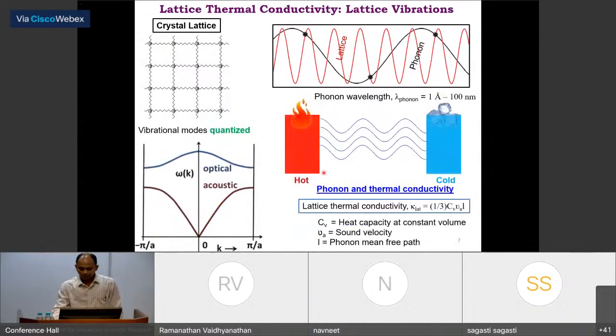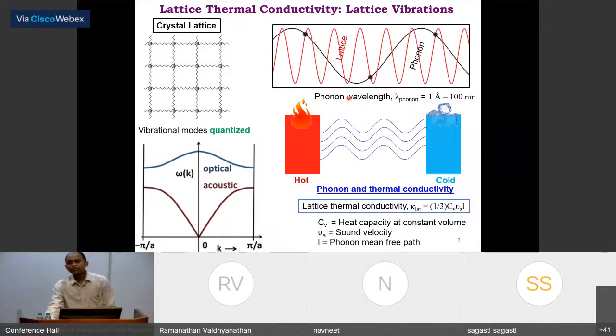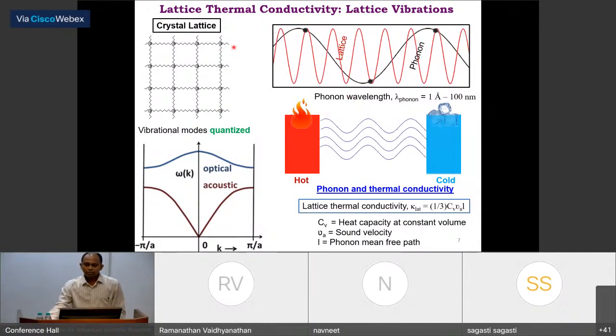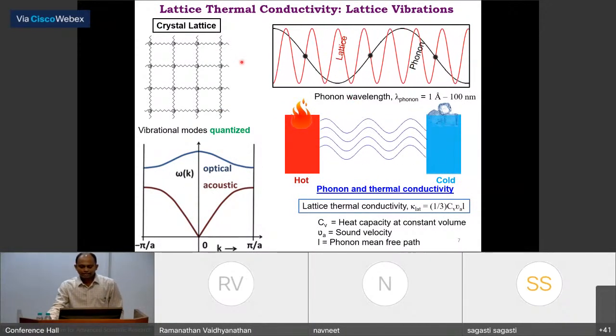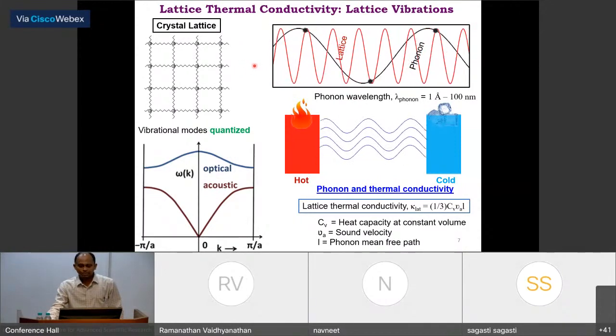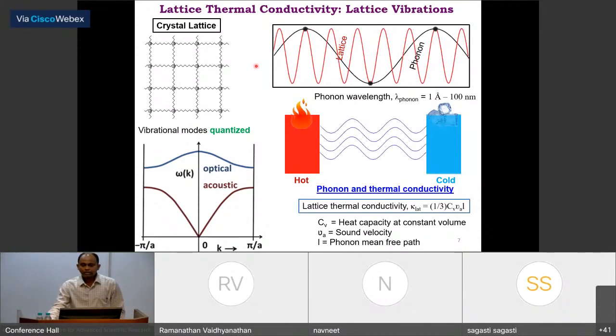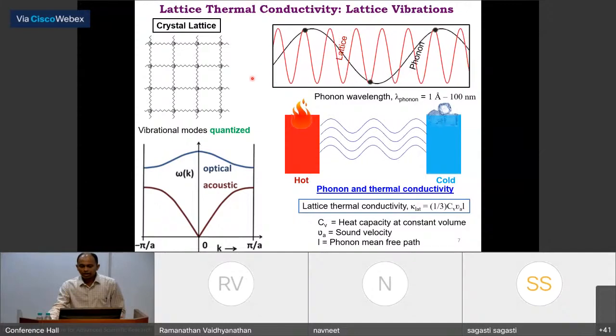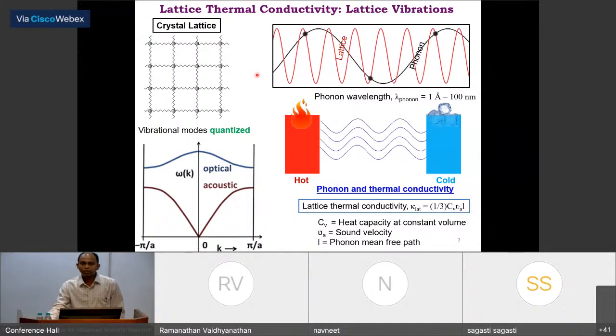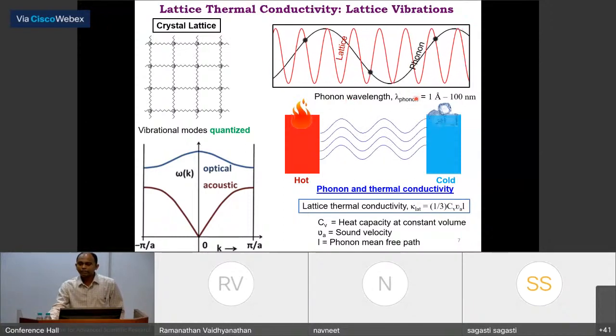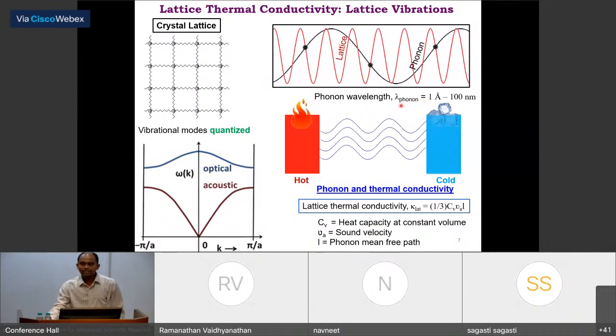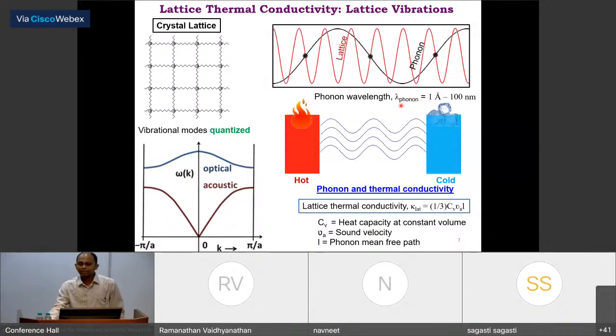So now I come back to this lattice thermal conductivity, which basically carries most of the heat in a solid material. So lattice thermal conductivity is nothing but how phonons carry the heat, and phonon is basically quantized lattice vibration, and the phonons which carry the heat in solid tellurides and selenides have a mean free path or wavelength of 1 angstrom to 100 nanometer. So in order to decrease the thermal conductivity, basically we have to block these phonons, right?